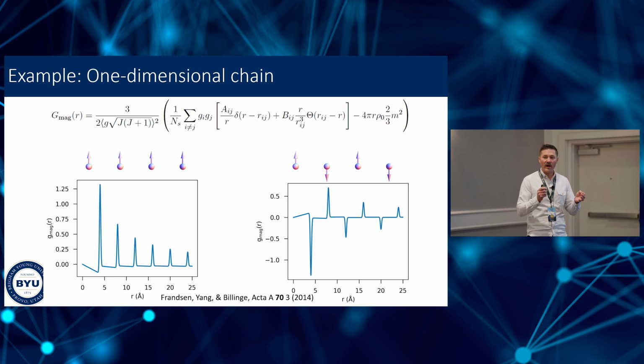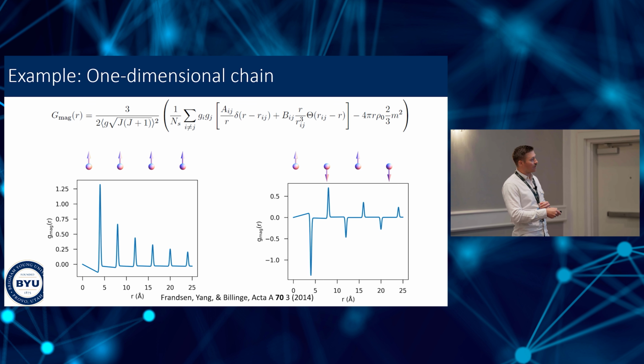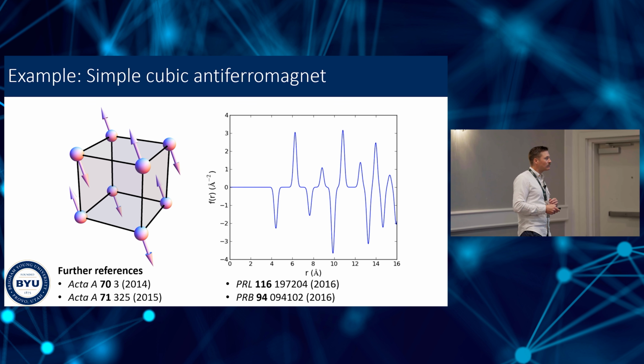Okay? And again, whether or not this is a long-range ordered magnetic state or these are short-range magnetic correlations, we are looking on the local scale here, so we'll be sensitive either way. Here's another example, a simple cubic antiferromagnet. You look at the nearest neighbor correlation here, which is opposite alignment between our spins. And so the first peak here is negative. The second nearest neighbor, we have parallel alignment, so the second peak is positive, and so on and so forth. Okay, so that's magnetic PDF in theory.